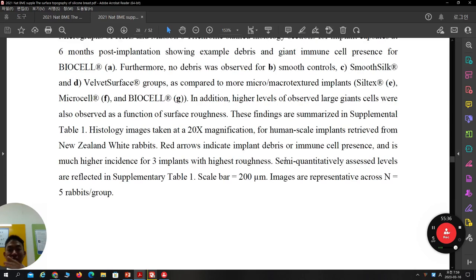So from this point, when you fabricate your material, and then suddenly your material debris is released easily inside of tissue, that can be an artifact of the tissue generation. They can cause severe inflammatory signal, and then that can affect your result. So that is why, when you coat something on the material like CNT or ceria, any kind of thing, when suddenly this kind of coating is released inside of tissue, that can be a player of the inflammation. That can cause macrophage signal a lot, M1 cytokine signal a lot, and then that can affect your final result. So that's why reviewers and many people ask about the coating or your material stability in tissue.